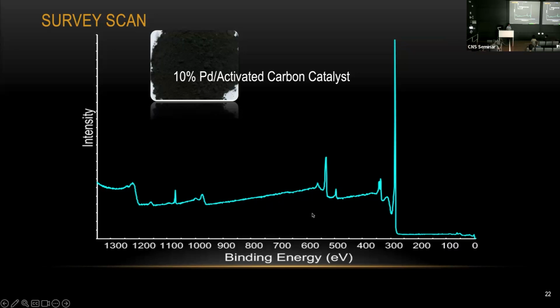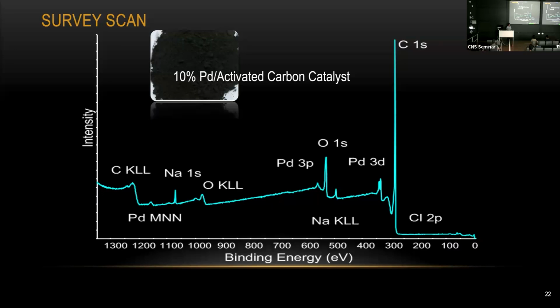The first thing, definitely, once you get this data, is you want to tell what kind of elements you have. So we need to identify which peak belongs to which element. You can see from the picture here, the very sharp peak right here is the carbon peak, because we are working on a carbon catalyst, so definitely we have a lot of carbon here. You also see the oxygen here and a couple of palladium signals here and there. During the XPS measurement, the process to get the electron out will also generate some Auger electrons, which we'll describe a bit more later. That's why you can also pick up some Auger signal here. So the oxygen KLL, carbon KLL, palladium MNN, all these are Auger signals.